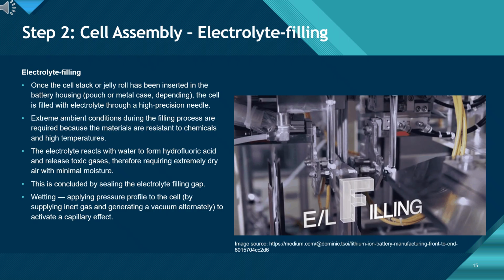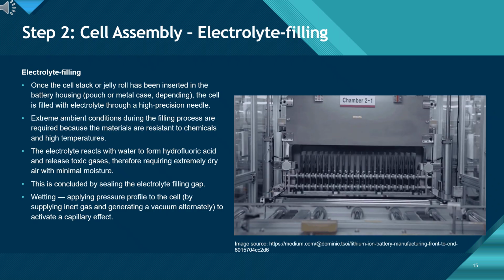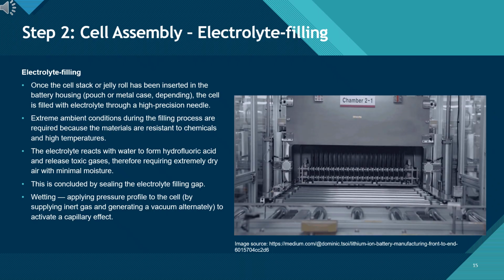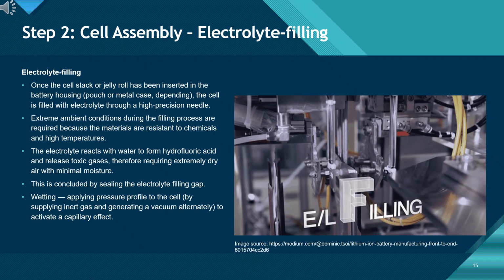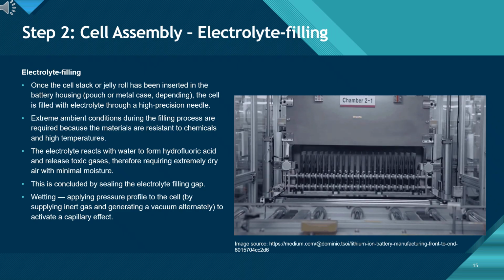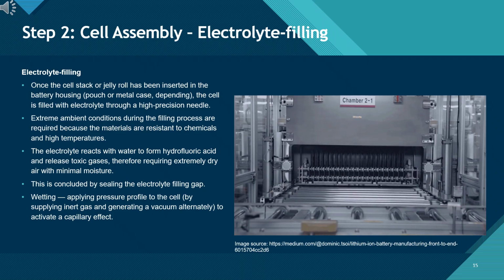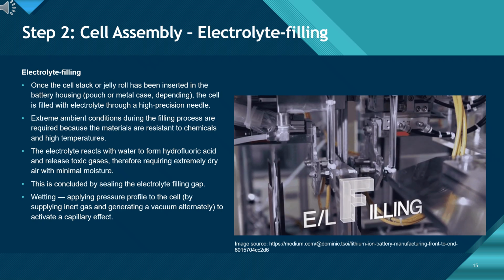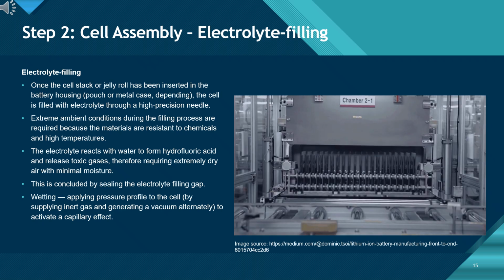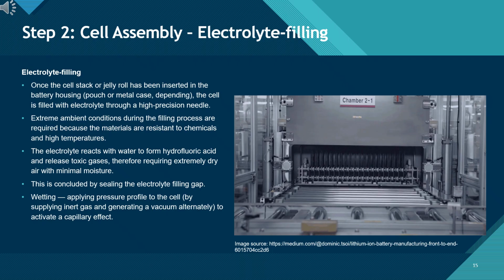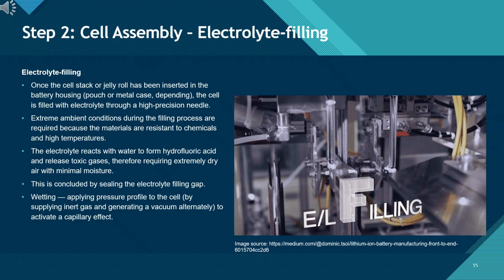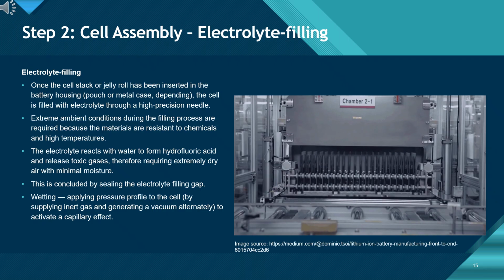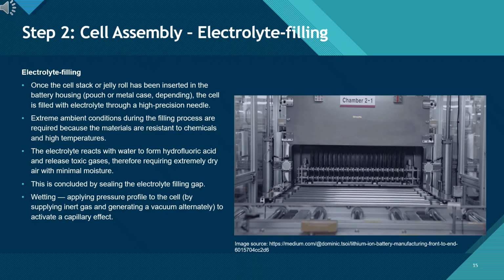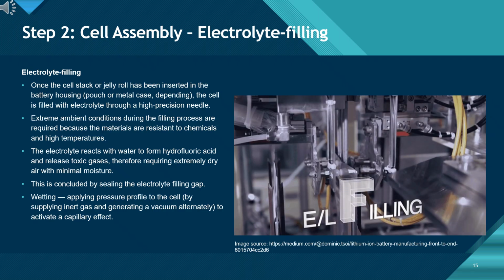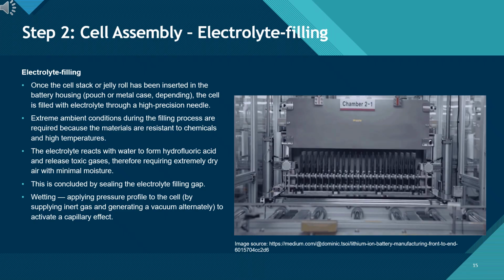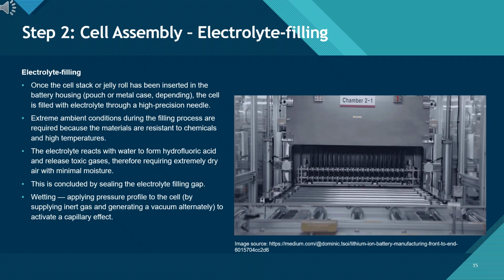After the electrode stack or jelly roll has been assembled and placed into its housing, whether a pouch or a metal can, the next critical step is filling the electrolyte. This process is carried out using high-precision needles to inject the electrolyte into the cell. Because the electrolyte is highly reactive, especially with moisture, this step must be performed under extremely controlled conditions. Even trace amounts of water can lead to the formation of hydrofluoric acid and the release of toxic gases. For this reason, the process is conducted in ultra-dry rooms with minimal humidity.